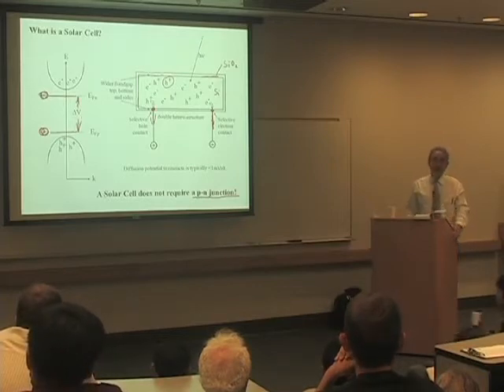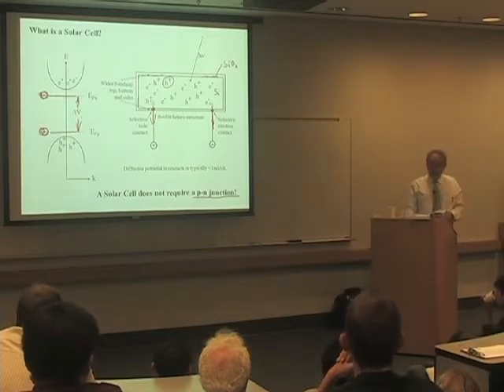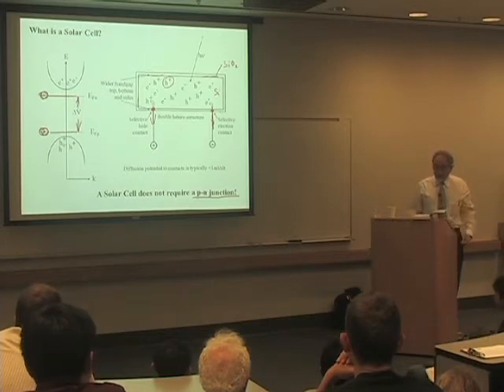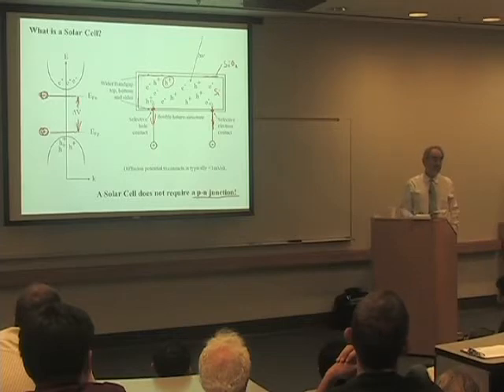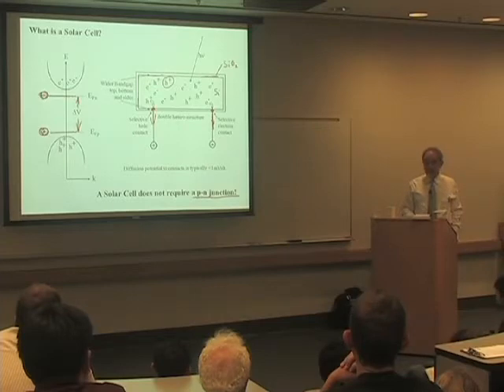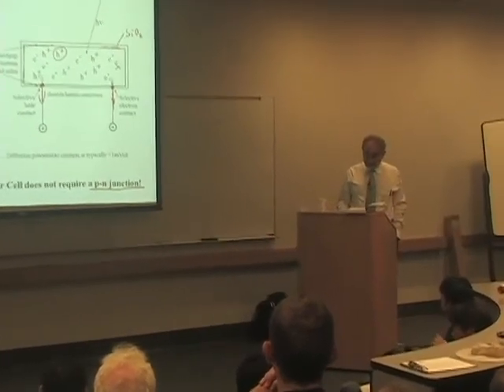Now you say, well, how are you going to drive the electrons to go to their contact? How are they going to know to go to their contact? And likewise for the holes. Well, it doesn't take much of a density gradient to push the electrons toward their contact and the holes toward their contact. And if you ask, oh, what kind of a density gradient do you need? It's just a few percent density gradient is enough to push the current through. And a few percent means you're going to lose a millivolt, which is pretty negligible. So moving the carriers around is not a problem. A millivolt out of a 1-volt solar cell is quite a small amount.